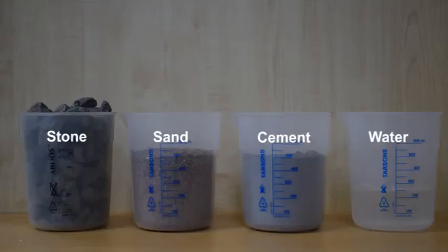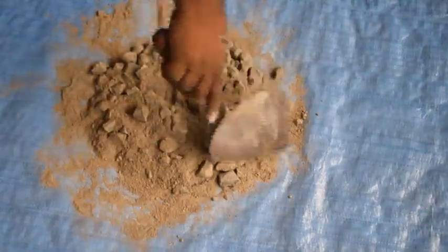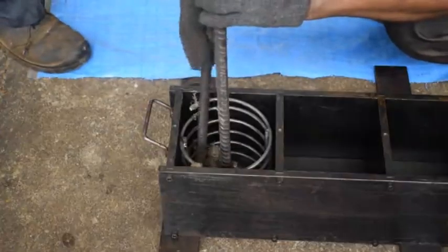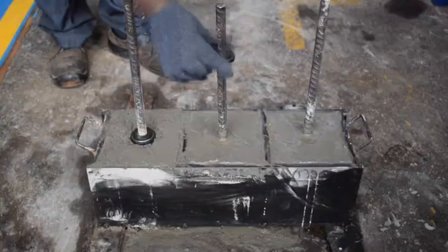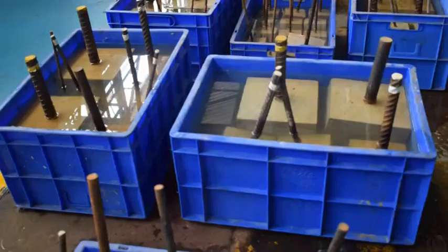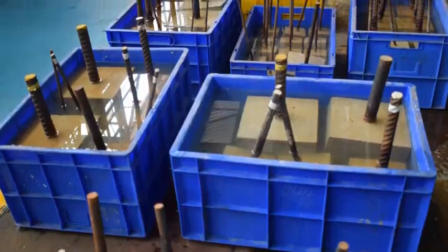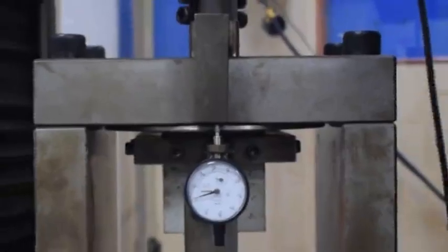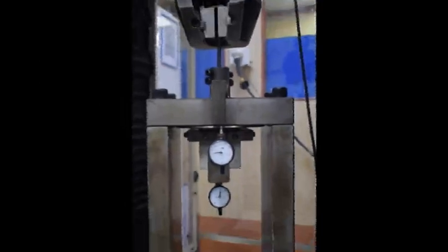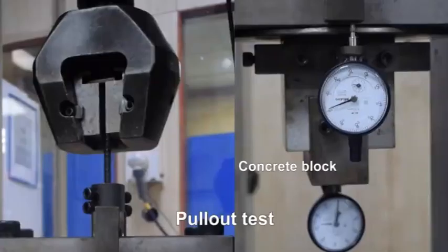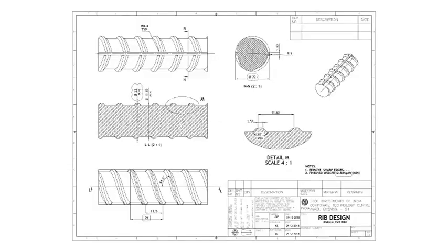projected rib area. The performance of rib geometry in terms of bond strength is routinely verified by type testing of the bars at the Technology Center by pull-out tests from blocks of concrete, where the force required to dislodge the bar is compared with bars of the same nominal diameter but without ribs. This kind of comparative pull-out testing is specified in the Indian standards, whereas the ISO standards specify the rib geometry permissible, which is independent of concrete characteristics.